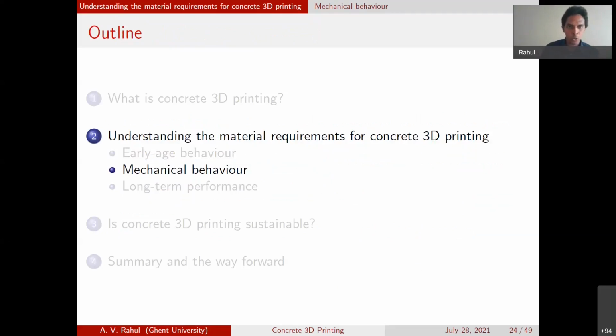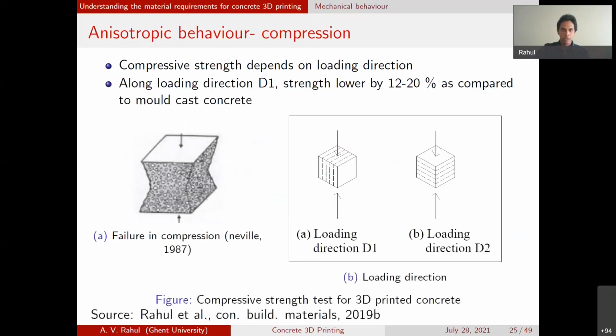Now, we also briefly talk about the mechanical behavior of printable concrete. One of the problems with printable concrete when we do, let's say, a compression test is its anisotropic behavior. If you test in different directions, you will get different compression strength values. This is something that we have to accommodate in design. For example, if your layers are oriented parallel to the loading direction, and if they are oriented perpendicular, then you might see a different strength value for both these cases.